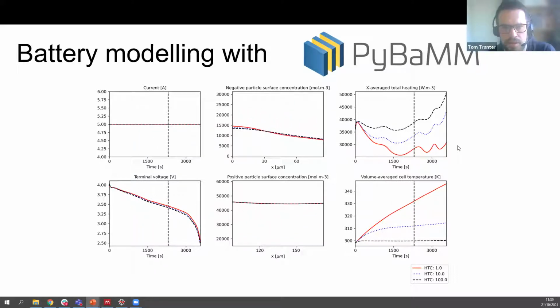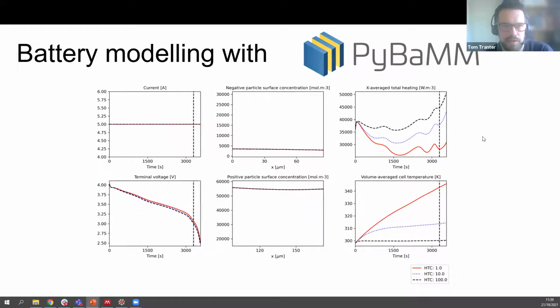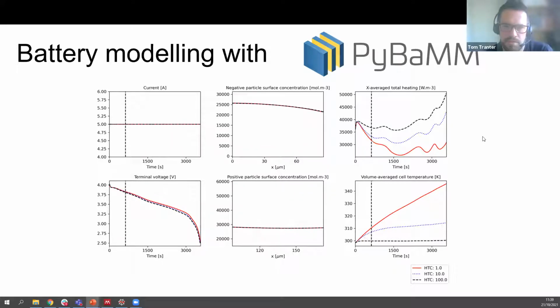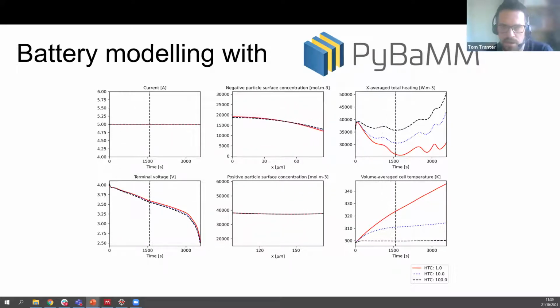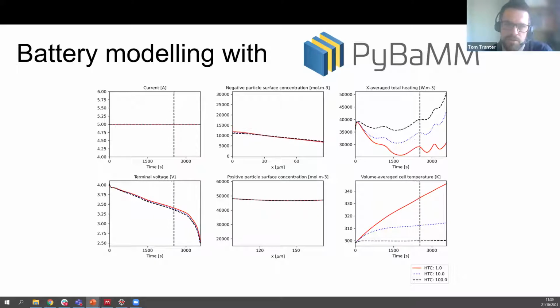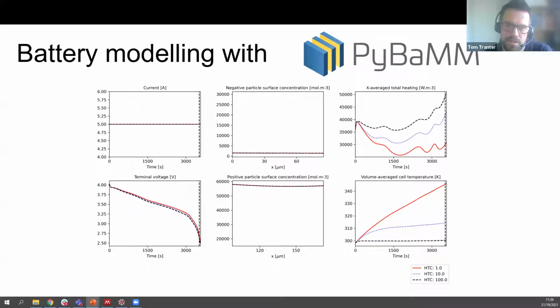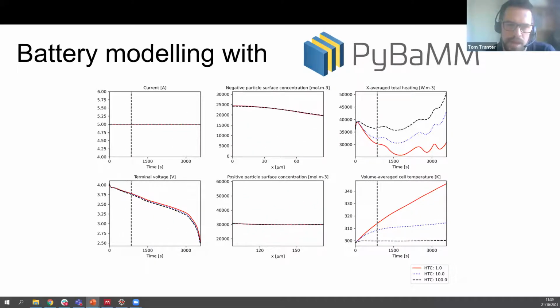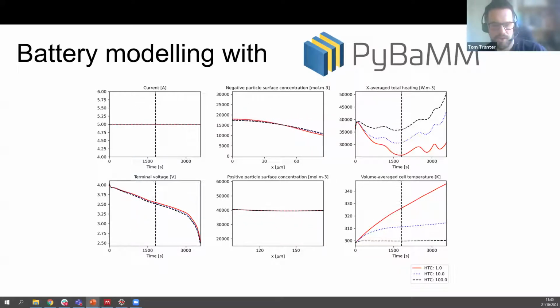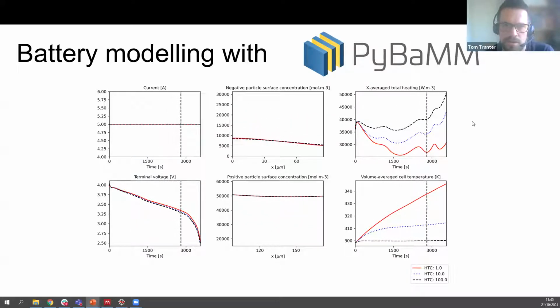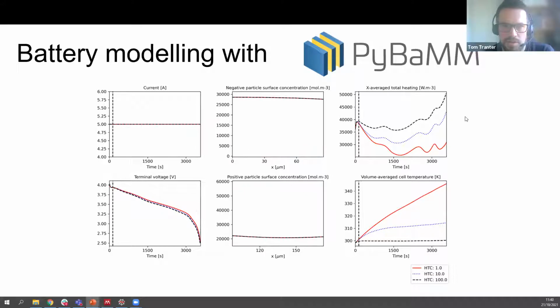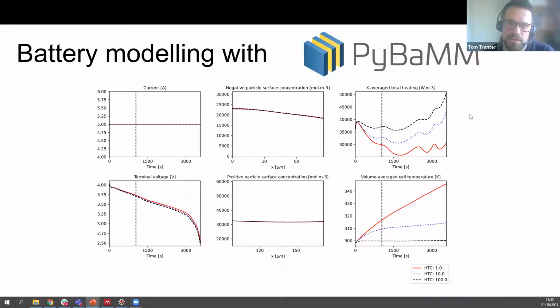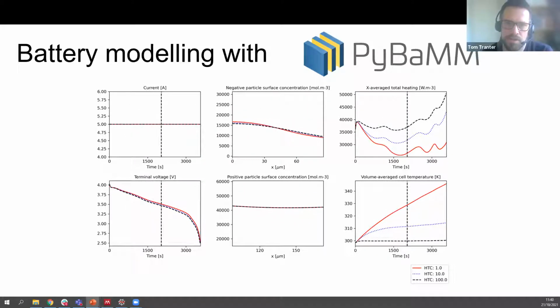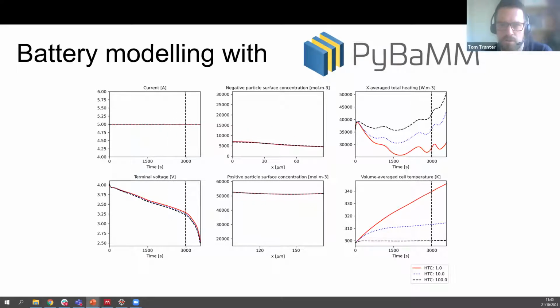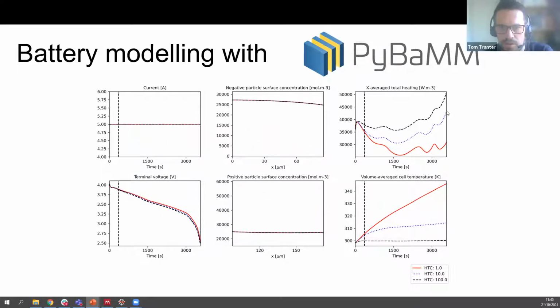So in a sense, we can use the acoustic response as a sort of internal temperature sensor, which is really cool because there's a lot of interest in thermal gradients within these cells, as the thermal, not just the absolute temperature, but the gradient itself will affect where certain regions of a cell will be degrading faster than others. And so this is quite a promising thing. It's a little bit annoying that the acoustic response is temperature dependent, but if you can control the situation enough, you can use it to your advantage, I think.